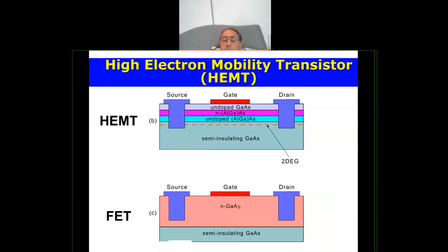To make it N-type, it means create electrons. For example, using silicon, you have to put silicon in this material, to dope it with silicon. And of course, when the silicon gives you electrons to be free, because it's group 3-5 and silicon is group 4, you will have excess electrons. The electrons will be actually moving in a region where we got a lot of positively ionized silicon atoms. So we got negative charge and silicon positively charged.